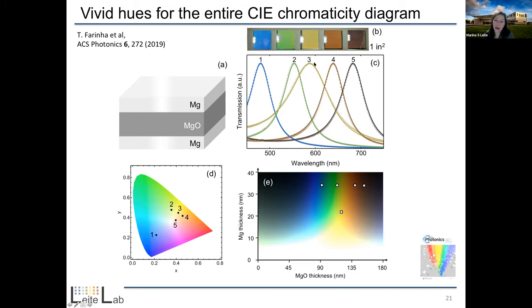For the yellow here, I'll recognize that the full width half max of this transmission curve is a lot wider. The reason for that can be explained by this plot. So we're gonna go clockwise here, okay? So essentially what you're seeing on the y-axis is the magnesium thickness as a function of the MgO. It turns out that all the samples are represented by these little white squares. So the students kept coming back and saying, okay, we think this is yellow. I'd say, no, this is pumpkin orange. This is not really yellow.